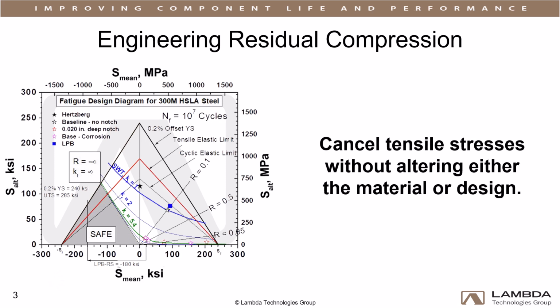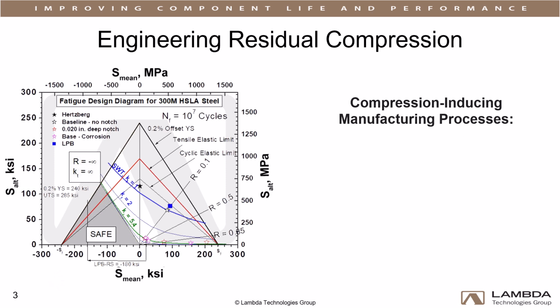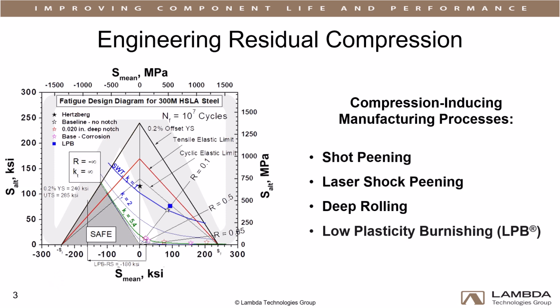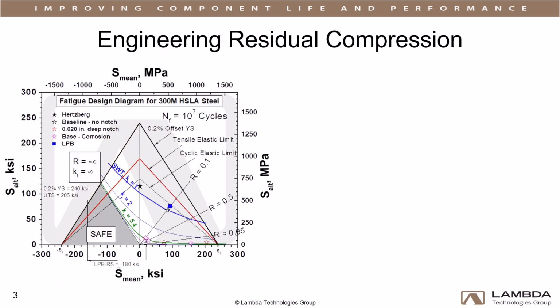Engineered compression can negate tensile stresses from normal operation without altering the original material or design. Compression can be introduced to the critical areas through mechanical surface treatments like shot peening, laser shock peening, deep rolling, or low plasticity burnishing. The depth, magnitude, and distribution of the residual compression are designed specifically for each component and application to optimize the part's performance.